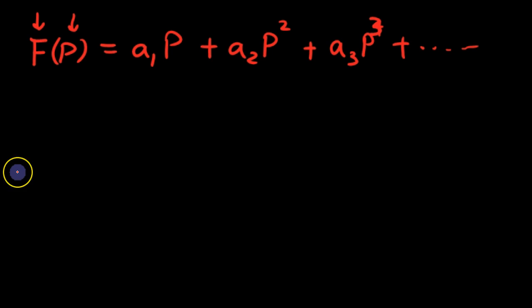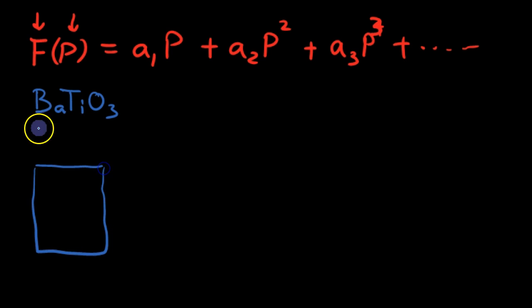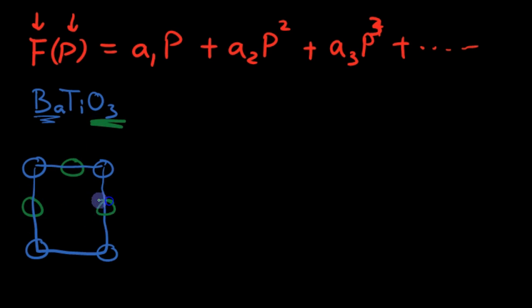We're using piezoelectric materials, but more specifically ferroelectric materials, namely materials which have a switchable spontaneous polarization. If we take our example barium titanate (BaTiO₃) and draw its structure: the corner atoms are barium, the face-centered atoms are oxygen, and we have a titanium atom in red. The titanium can either be displaced above the midline of the material or on the bottom.